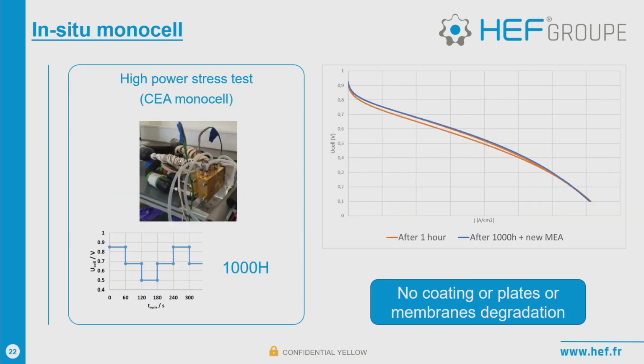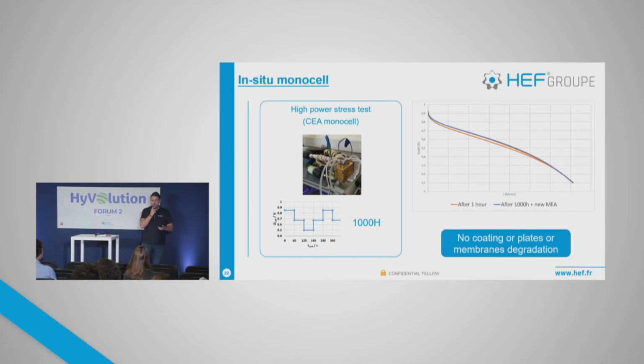And last thing, which is really, really important, is the coating degradation. We have made several tests with several laboratories. This one is a high power stress test done with the CEA for 1,000 hours. In fact, you have two curves, which seem to be the same. The first one is after 1 hour, the orange one, and the blue one is after 1,000 hours. So in fact, with our coating, after 1,000 hours of stress test, equivalent to 10,000 in real life, you have no coating, neither plates, neither membrane degradation.